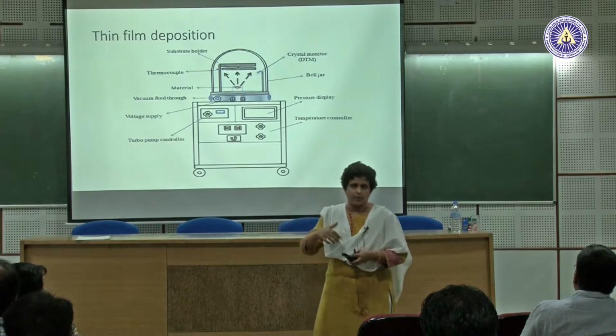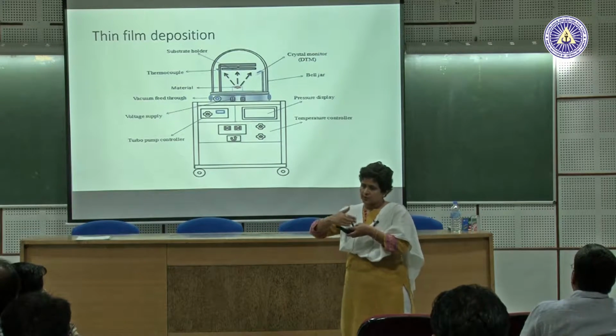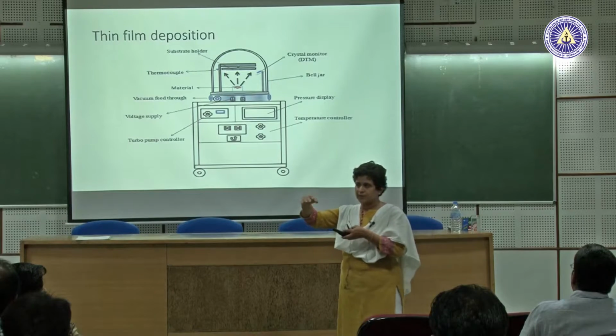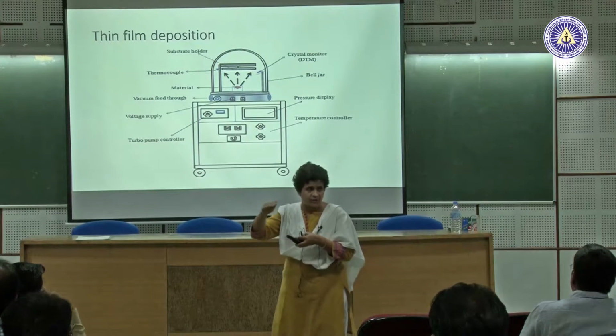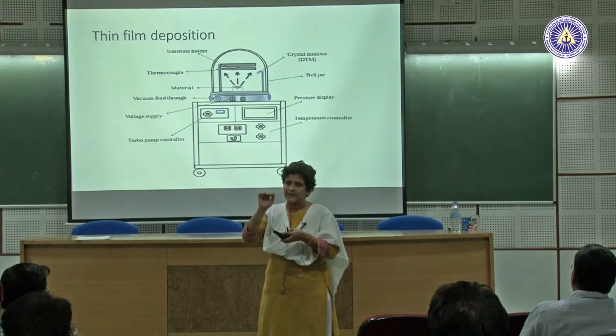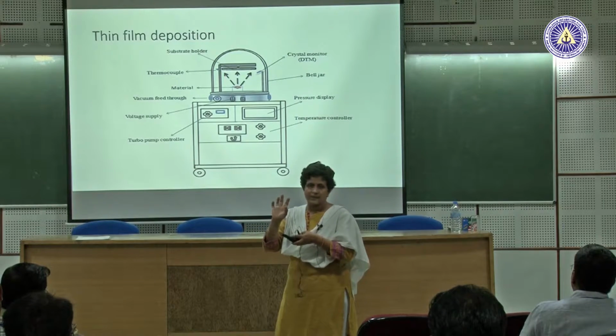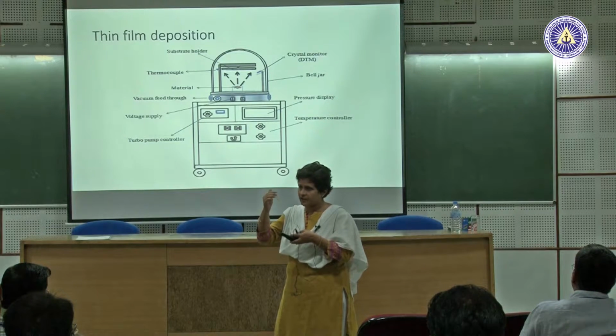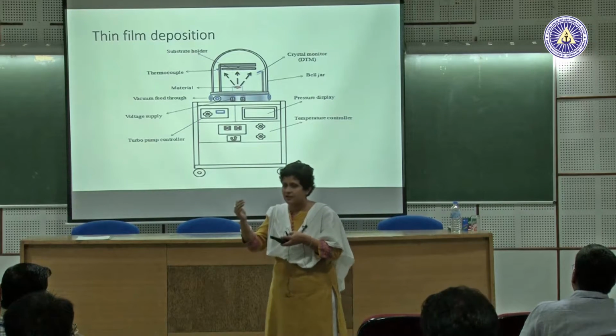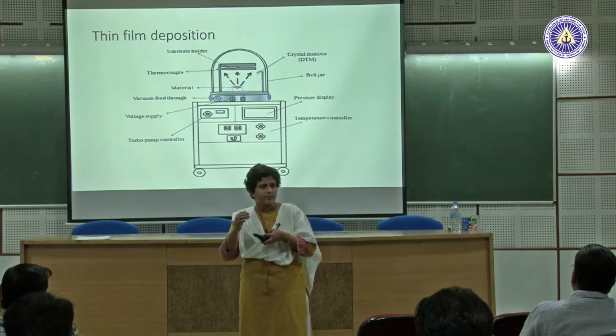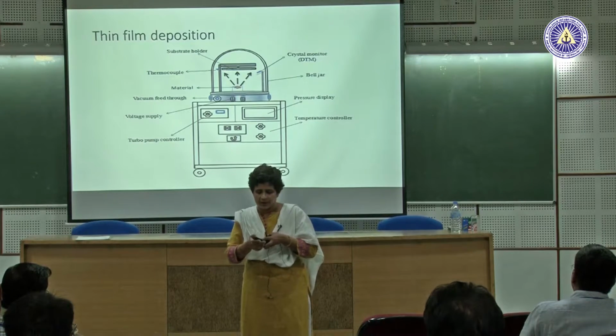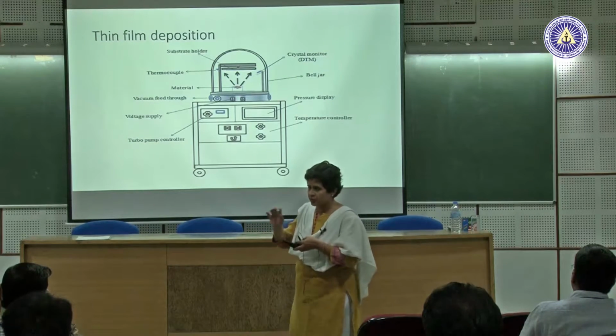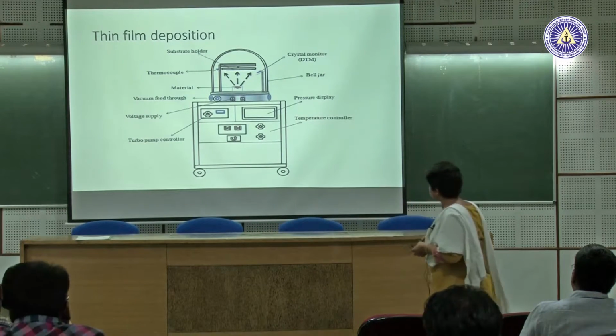So, from a manufacturing point of view, you are depositing a film on a surface, right. So the cleanliness of that surface is important. If there is any contamination on that surface and you bring the vapor phase and it gets condensed on that, the strength of the joint between the substrate and the film depends on how clean that interface is. So that is very important when you are doing thin film deposition, to make the surface proper.